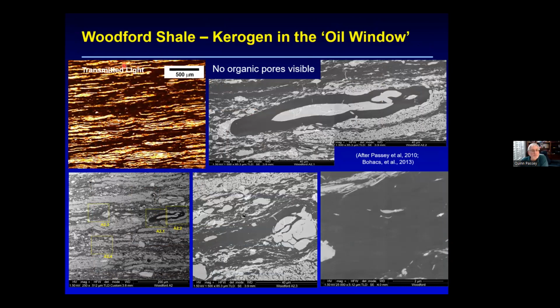Now, when we zoomed in to this, again, this is in the oil window. Here's one of these Tasmanites cysts, and we zoom in, and we couldn't see any organic pores. And so that's where we started saying, well, it looks like the organic pores form, at least in the kerogen, in the latter part, just before you're starting to go into the gas window.